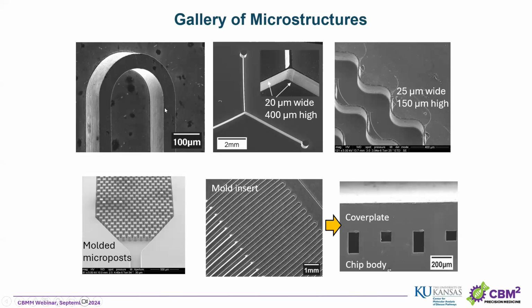SEM images of microstructures, the top one milled in brass. And you can see how here we can machine very high aspect ratio structures with only 20 micrometers wide and which are 400 micrometers high. And it came from the fact that we actually machined everything around it, right? So only these structures were left. So we can push the limits of what size structures can be made with micromilling by using this replication route.